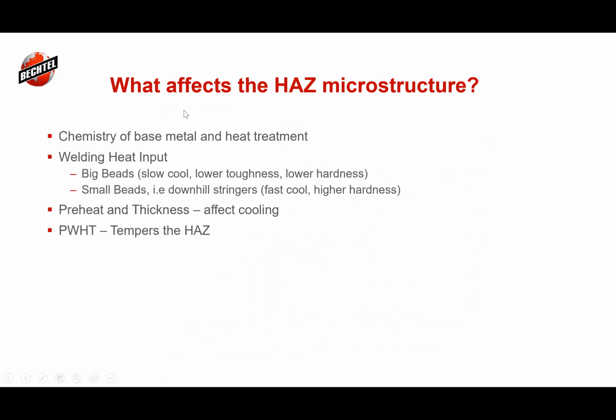So when we talk about the heat affected zone, I'm going to get into the carbon steels. Obviously, the chemistry of the base metal and the heat treatment are going to be really important. A36 is on one bookend and 514s are on the other side. But we have a lot of other alloys that we all deal with that are somewhere in between, with a wide range of base metals and heat treatments, whether it's normalized material or quenched and tempered materials like a 537 class 2, I think is quenched and tempered. Testing my knowledge there off the top of my head. But you get the chromoly steels, and then the 514s obviously are really critical.